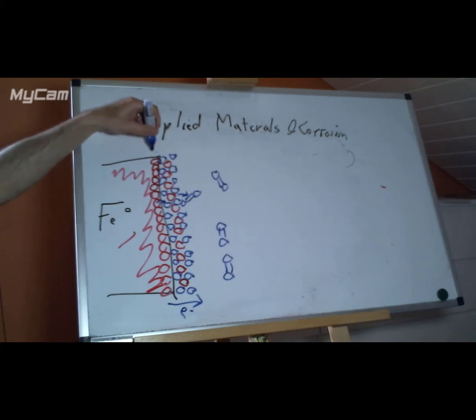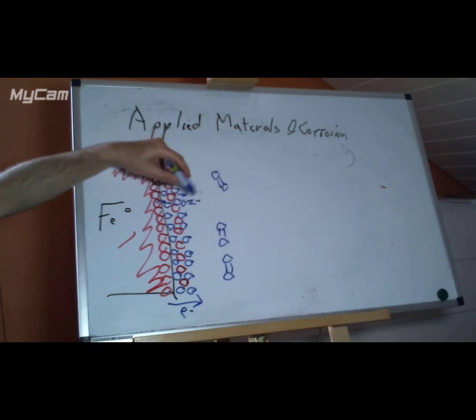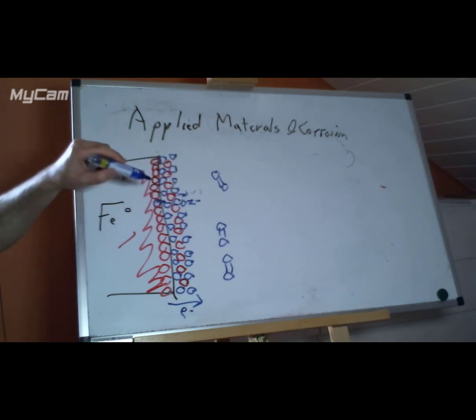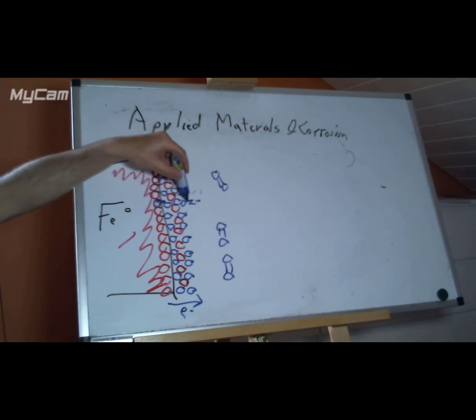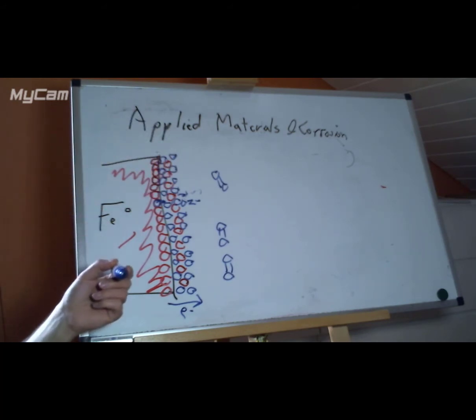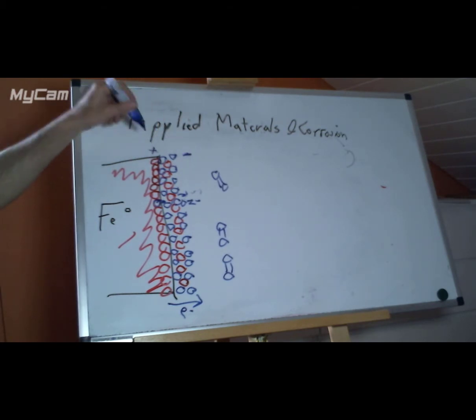And the problem is that the O2 minus that we've made on the surface is stuck out here, and the iron 2 plus or 3 plus, depending on which it is, whoops, I've drawn that in blue, is stuck in here. So we've got this one and this one, and they really should be coming towards each other, otherwise we haven't got iron oxide. So until they can combine with each other, we have generated a negative charge on the outside and a positive charge on the inside.